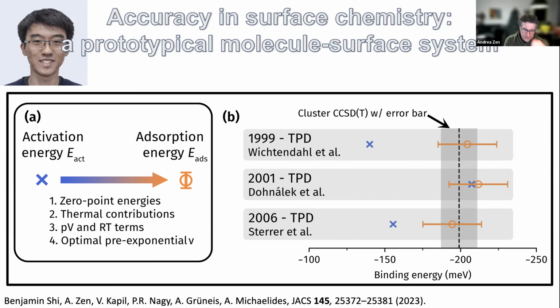And the most important thing that we saw is that there is a pre-exponential number that is applied. These three experiments, for instance, didn't use the same pre-exponential number. So if you try to see which pre-exponential number makes the results more in agreement with our simulations, and you apply the same number to all three of them, they move to the new values that you see here, which are indeed in agreement with our theoretical estimation.